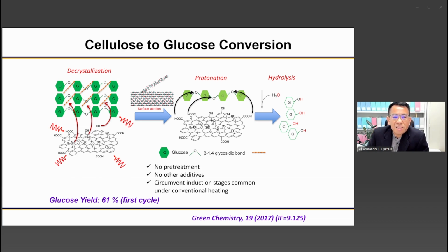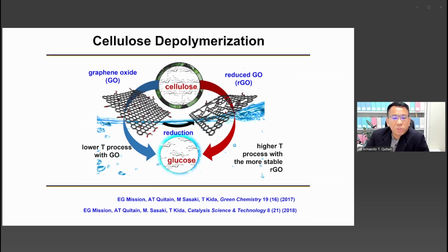And this is due to a very high affinity of graphene oxide with cellulose. So the process undergoes surface attrition first, followed by protonation that will aid hydrolysis of cellulose in order to get glucose. The results actually are published in Green Chemistry.